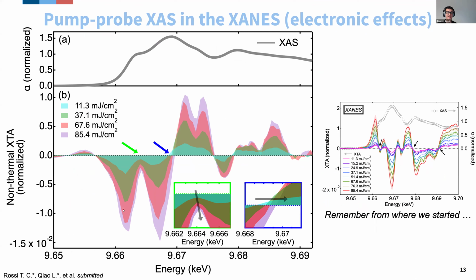And when we look at this line shape and we compare it with the equilibrium spectrum in gray, what we notice is that this looks pretty much like a first derivative line shape. So you have two negative features followed by two positive features. So it looks like these non-thermal transients actually correspond to the spectrum moving to the right. It's blue shifting.